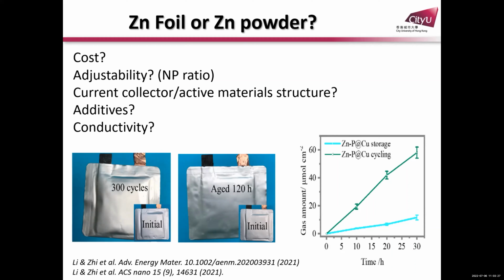If you want to adjust the NP ratio, for example, with zinc foil you cannot have continuously different thicknesses. And also the current collector and active material, if you use zinc foil, are all together, right? Zinc foil works as an active material and also a current collector. At a low zinc utilization, it will be fine. But if you go for high zinc utilization, you get a big problem because the conductivity can be much worse. And it's difficult to add additives to zinc foil.